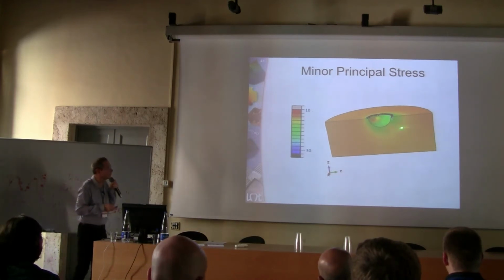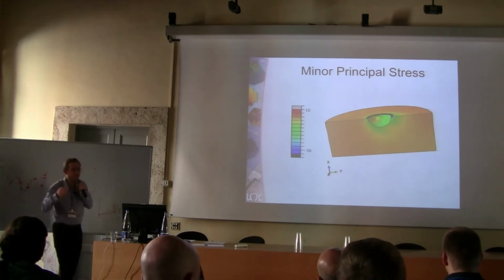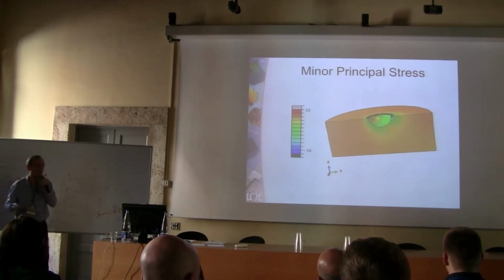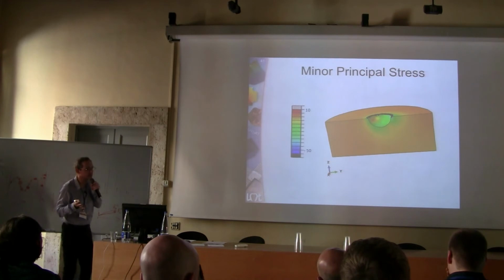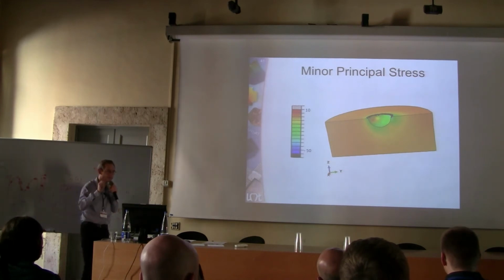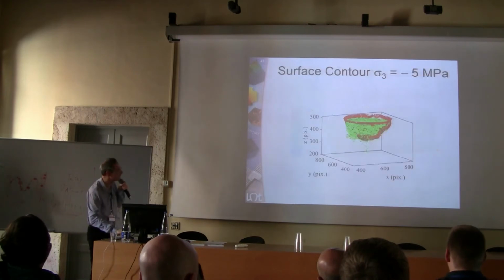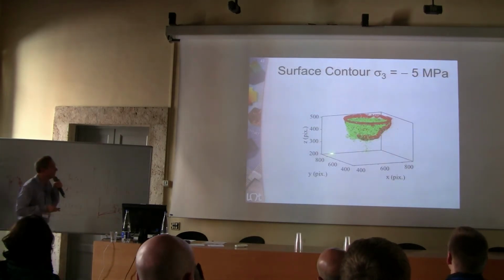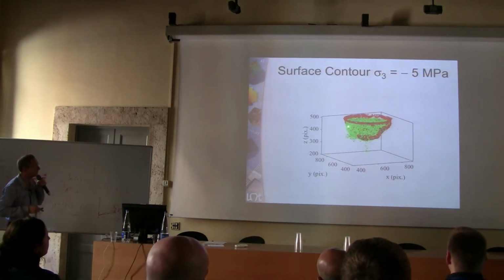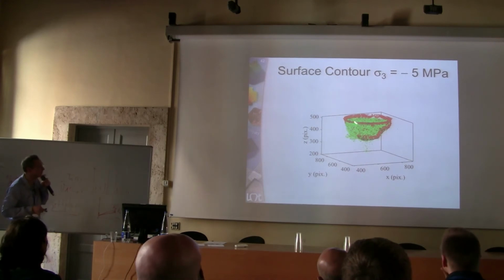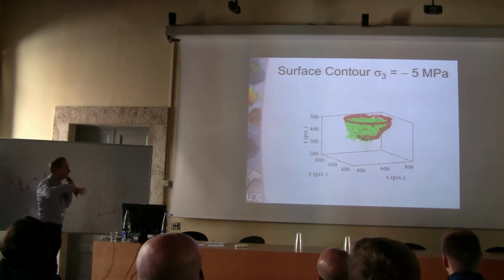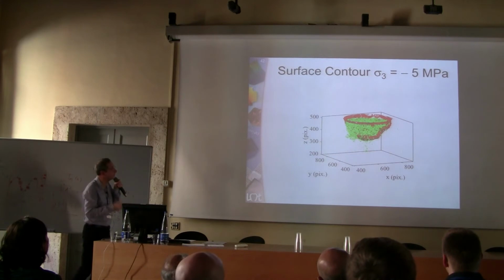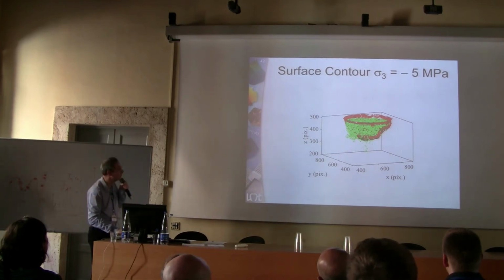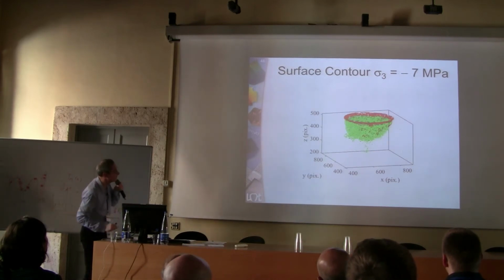So now the question will be, for different stress contours, which one best matches the transition between the pristine and the crushed zone. Here is the comparison between the residuals in green, and the red one is this stress contour for minus 5 megapascal level, minus 6, and minus 7.